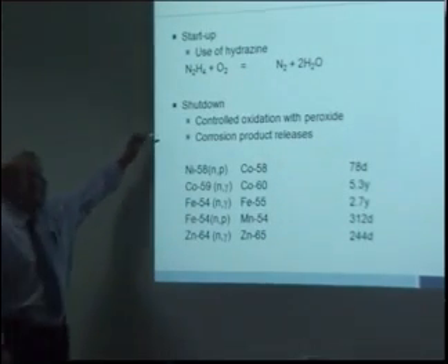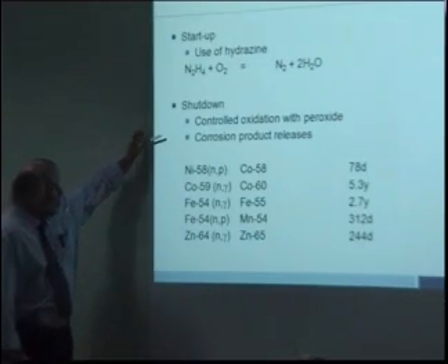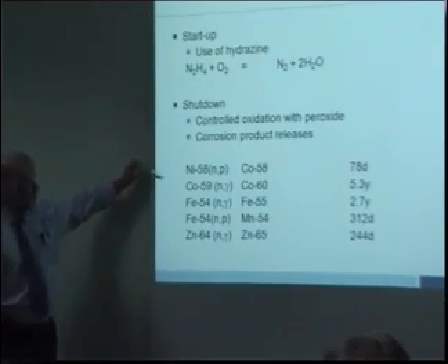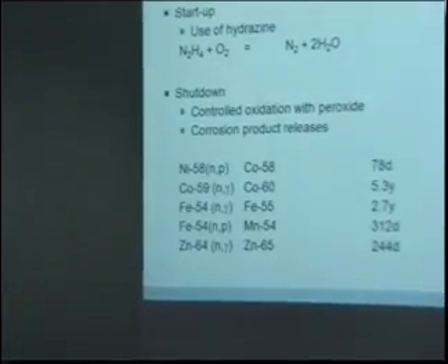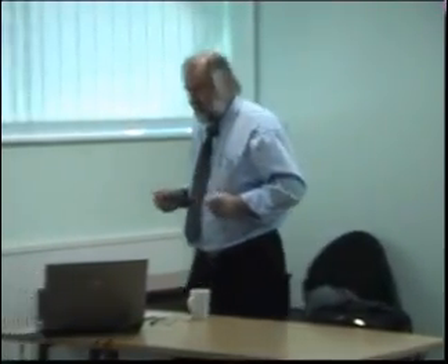So this is what happens. Unfortunately, when you go into oxidizing conditions, all the transition metals, which were normally in the +2 oxidation state, go over to the +3 oxidation state, and they will dissolve. They will become soluble, and furthermore, you have particles spalling off the surfaces. So this effect during shutdown is called a crud burst, and you get a massive peak, several orders of magnitude increase in corrosion product activity in the coolant. This is not a problem. It's taken out in the chemistry, in the chemical volume control system.